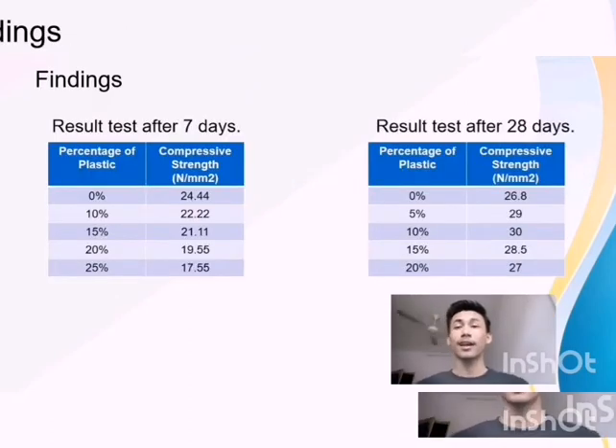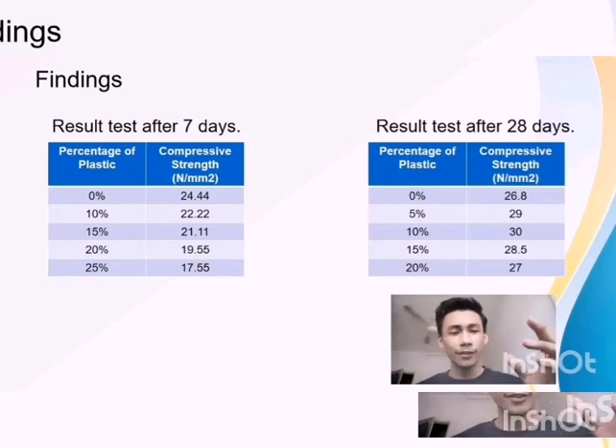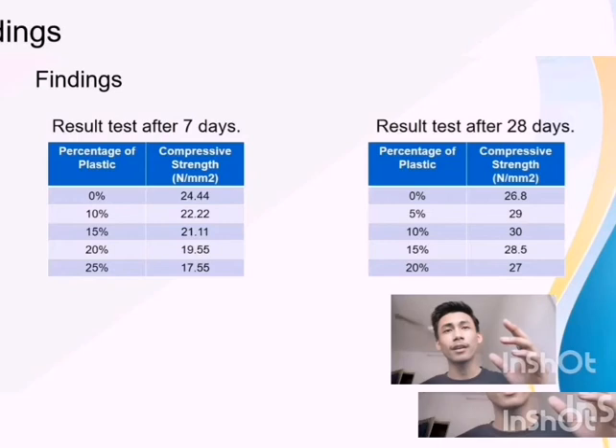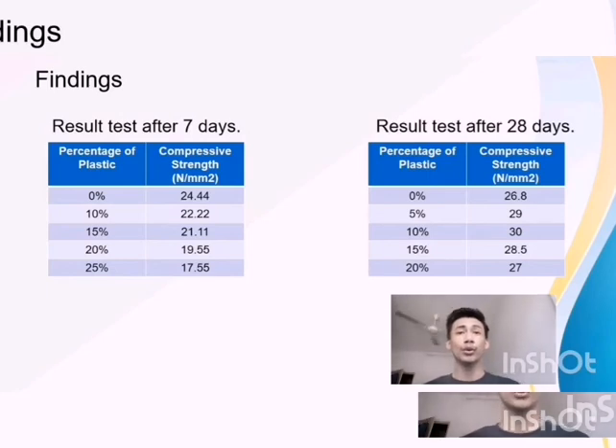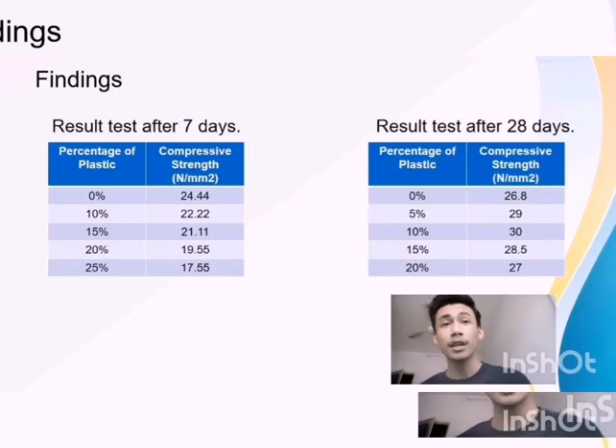So next we will continue with the findings. For the results shown in the slide, at 7 days, the natural concrete with no plastic has a compressive strength of 24.44 Newton per millimeter squared. For 10%, 15%, 20% and 25%, every percentage increase reduces the compressive strength further. 10% has 22.22 Newton per millimeter squared, 15% of plastic has 21.11, 20% is 19.55, and 25% of plastic has a compressive strength of 17.55.